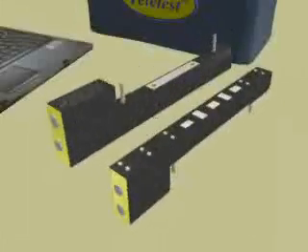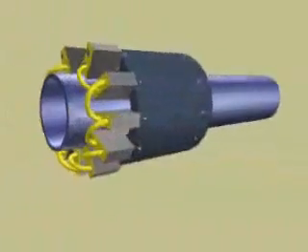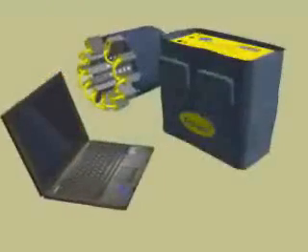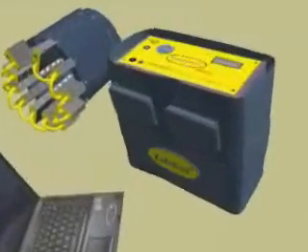It's an ultrasonic system, but its transducers — these parts just here — are pressed against the pipe and operate at several tens of kilohertz, as opposed to megahertz frequencies used in conventional ultrasonic testing. So a special flaw detector is required — that's what this box does over here.